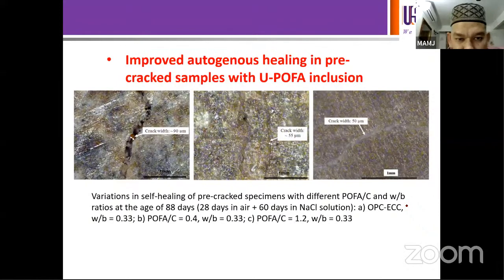And the potential of the material to undergo autogenous healing in pre-cracked samples was also observed. So in the case of the first one here, it is OPC ECC, meaning without POFA. So we can see a significant crack of about 90 micron. And the second one, B here, with POFA over cement ratio of 0.4, has a slightly smaller crack width. But in the case of the third one, POFA over cement of 1.2, the crack is about 50 micron, but we are seeing that it's almost close.